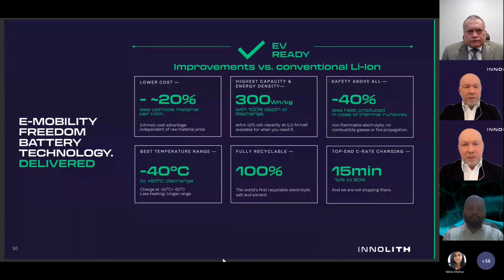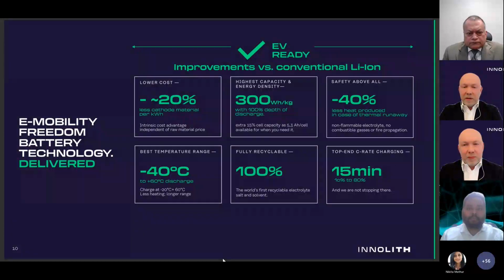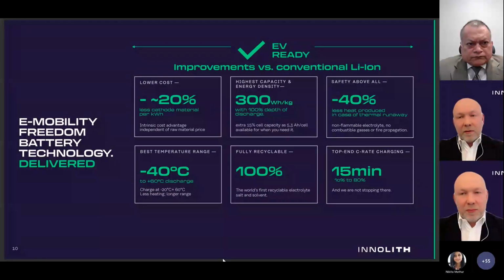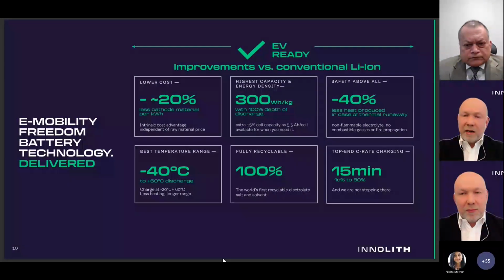Then on the lower temperature performance, as I've mentioned already, the cell can be discharged at -40 and charged at -20, and approximately 80% of capacity would still be available. The electrolyte is fully recyclable, and that is also a strong differentiation from organic electrolytes, where normally electrolyte salts cannot be recovered during the recycling process. On fast charge, 15 minutes is just an average which is required for electric vehicle applications, but we've managed to achieve significantly higher rates of 7C, 8C, up to 10C, which would be 5, 6, 7 minutes of charge and discharge time. Next one, please.